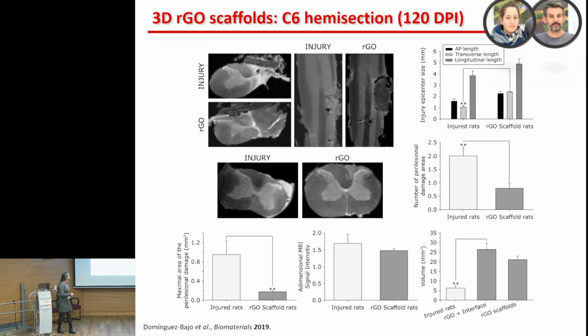So this was very positive, but it was even more positive to find that in other areas that were not exactly at the lesion site, but a little bit away from it, the number and maximum area of lesions still showing damage, what we call perilesional damage, were much reduced in the rats that had our scaffolds in comparison with just the injury. So it's not only a positive effect at the lesion site, but if we move a little farther from that area, we also get a positive influence of our scaffold.